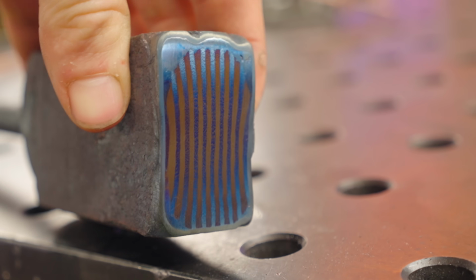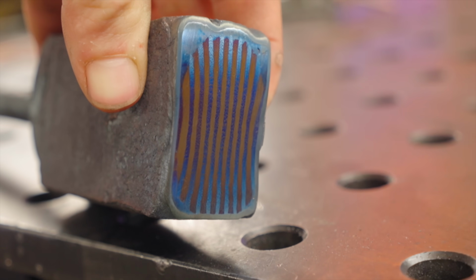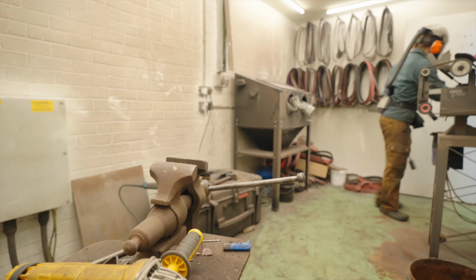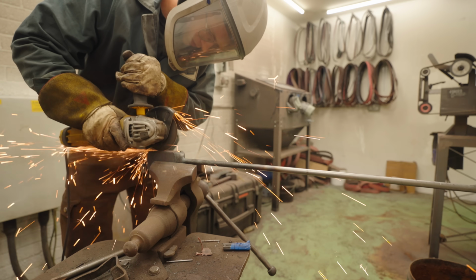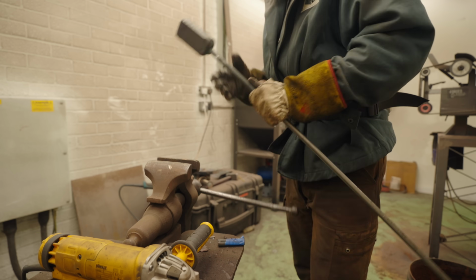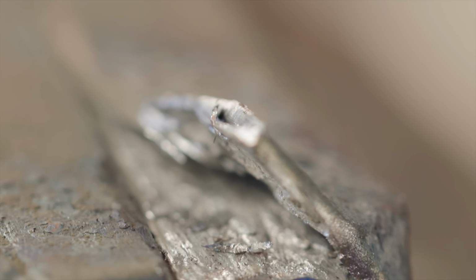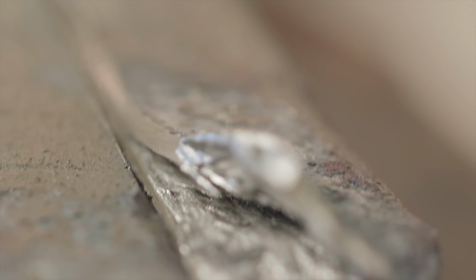Now I must say, it looks remarkably well stuck to the titanium, which does leave me wondering, maybe there's going to be the opportunity to actually do that steel and titanium forge welded combination that I tried to do 6 years ago. So much experimentation, I can't wait to get stuck into. There was definitely some sort of bond between the titanium and the steel, but it's clearly not super strong.